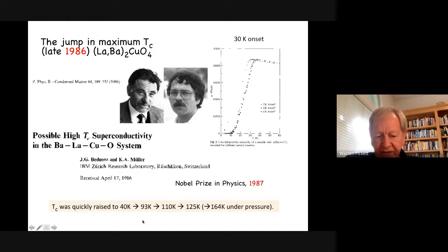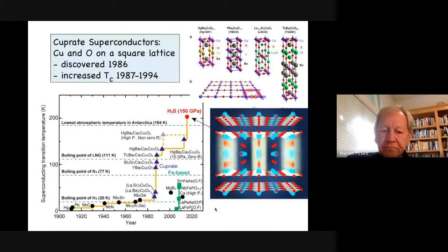Okay, and then after this, in cuprates, TC was raised quickly from 40 Kelvin when this was cleaned up, to 93 Kelvin in yttrium barium copper oxide, to 110 Kelvin, 125 Kelvin, and applying pressure, even in this mercury compound, 164 degrees Kelvin. That's still the highest critical temperature for a cuprate superconductor.